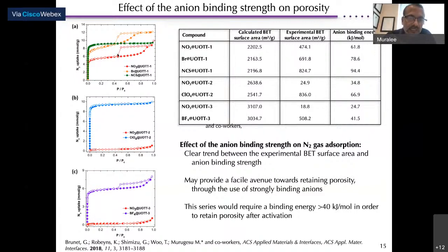But one thing is clear, when you have these nitrates or the bromide anions, you have this reversibility or hysteresis. Basically, the hysteresis tells us the mobility within the framework is leading to this hysteresis, or maybe the partial collapse of the framework. Whereas if you have strongly binding anions, such as NCS, then the framework is stabilized. You can see in this table of the BET surface area, the more you go to the stronger binding anions, the more you are stabilizing the system. Now this BET surface area is much better. So in this case, above 40 kilojoules per mole of binding energy, you are stabilizing your system. So although this shows that it is exchanging, the stability is still a concern for us.